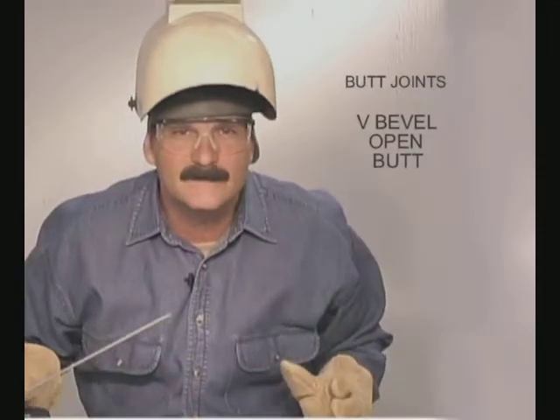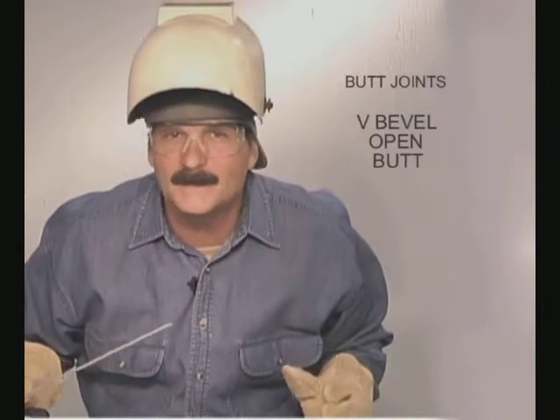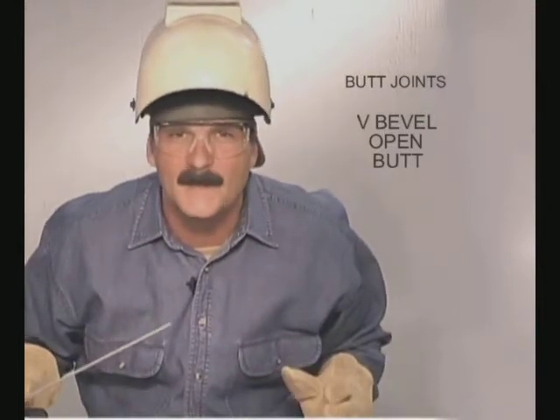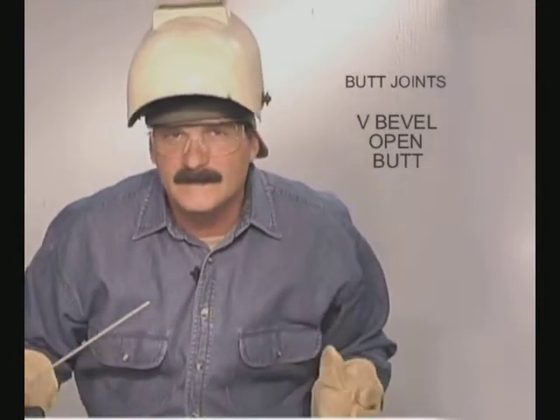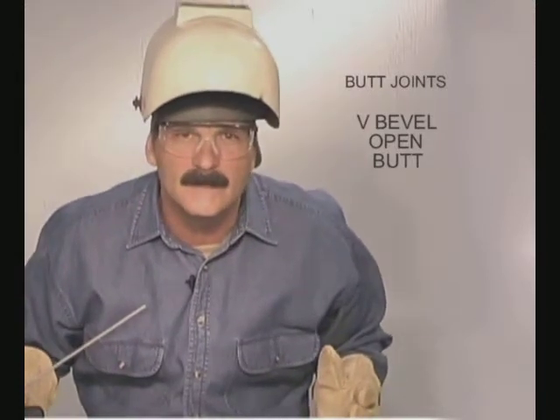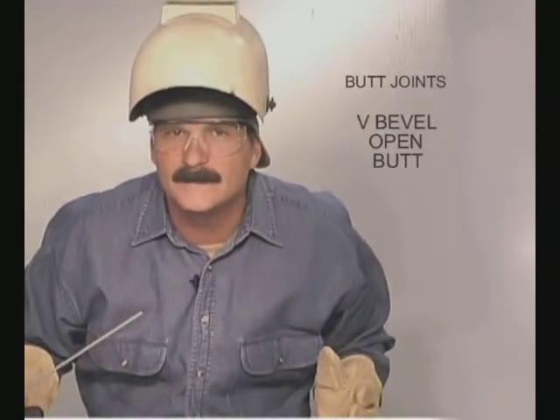Other welders like to leave a little thicker landing and wider gap, here again using a step motion, laying metal in and making sure it's fusing on the bottom corners. The disadvantage to stepping the root is the possibility of undercutting along the edges on the back side. The advantage is that you actually see the root going in for 100% penetration.